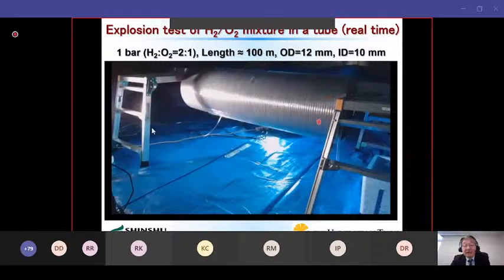And here I will show you two typical experiments of this kind. In this case, we use polyvinyl tubes. The inner diameter is 10 millimeters, and the total length is 100 meters. Inside of this tube is filled with 1 bar of hydrogen and oxygen mixture in a 2:1 ratio. And here we have a spark plug to cause the explosion.